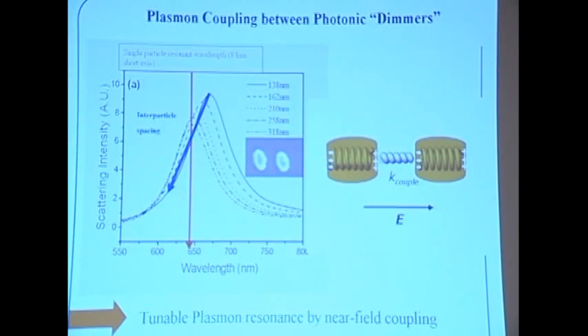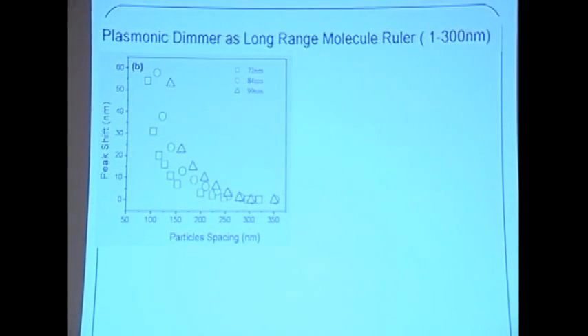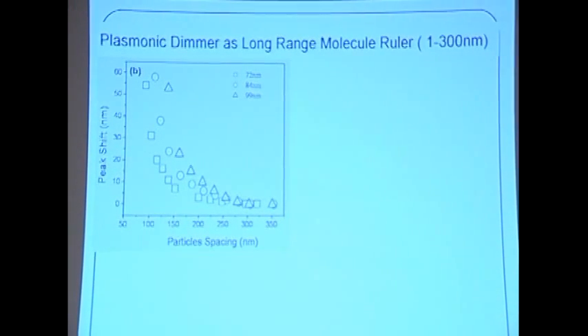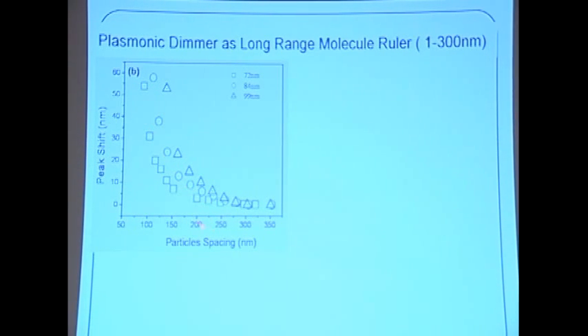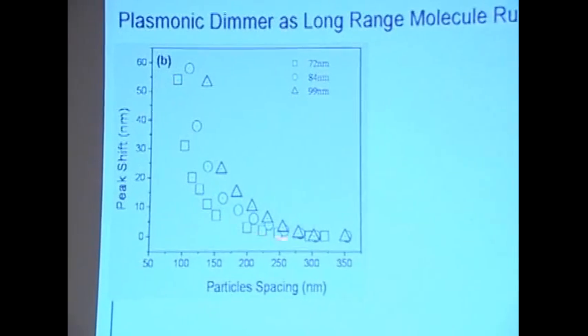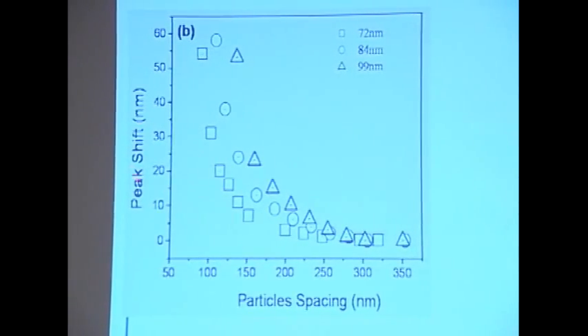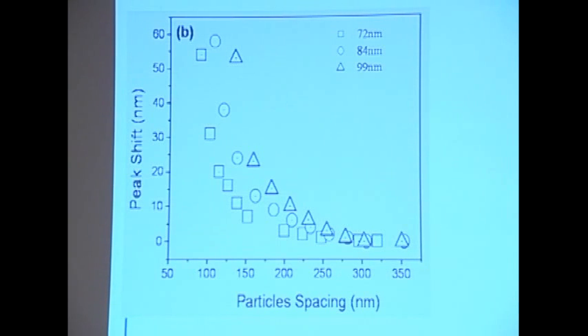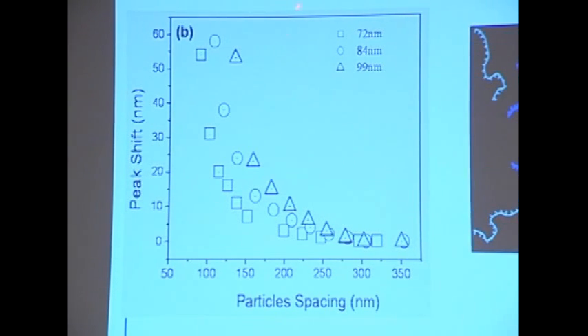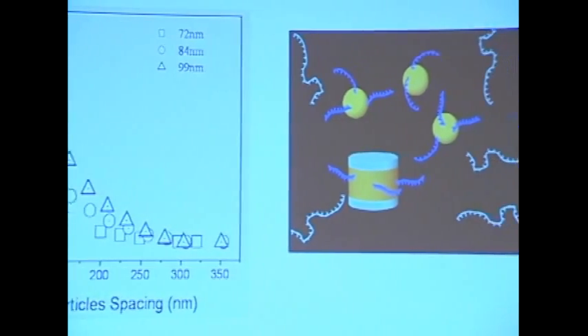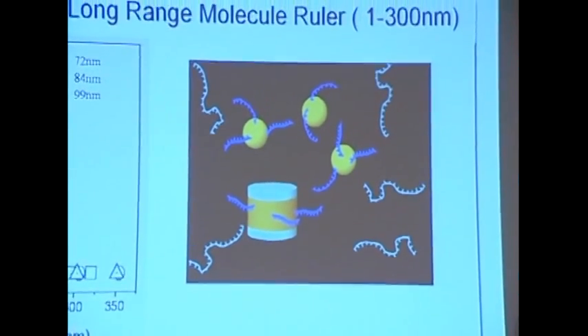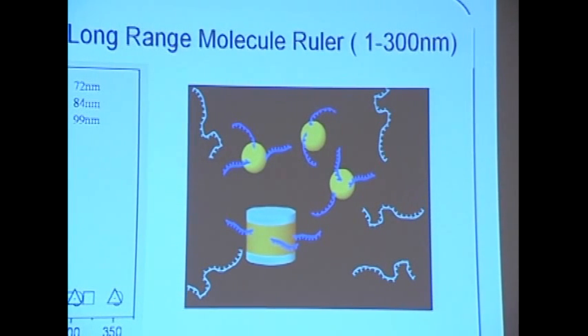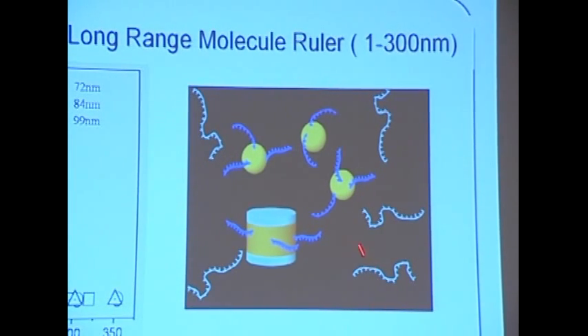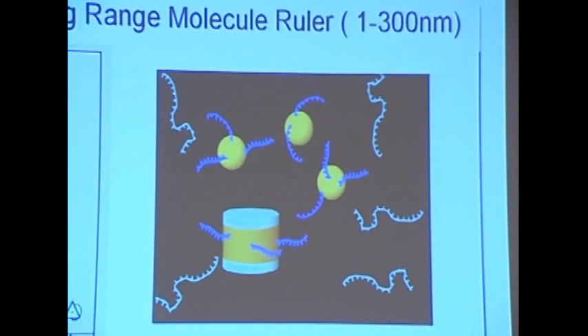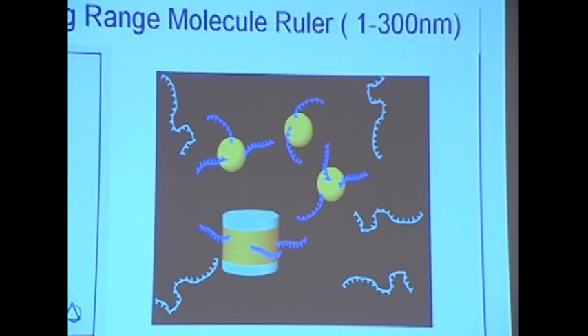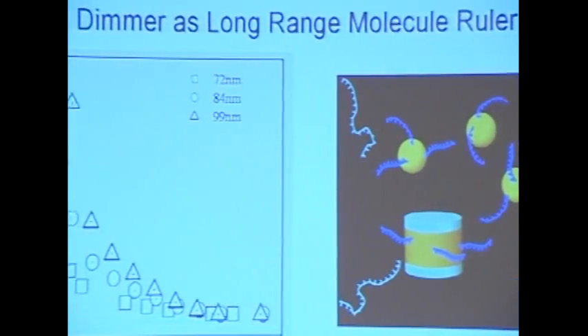We also did the FDTD simulation, which I'm not going to show here. So why is this interesting? What we demonstrated in 2003 is that if you plot the redshift versus particle distance, it is a monotonic dependence. So by reading the peak shift, you can determine the particle spacing. That gives you the possibility of a so-called plasmonic dimer as a long-range molecular ruler. For example, if you have two nanoparticles with DNA or any organic or biomolecule in between and you don't know the length, by looking at the overall system resonance redshift you can tell the distance between them from a single curve dependence.